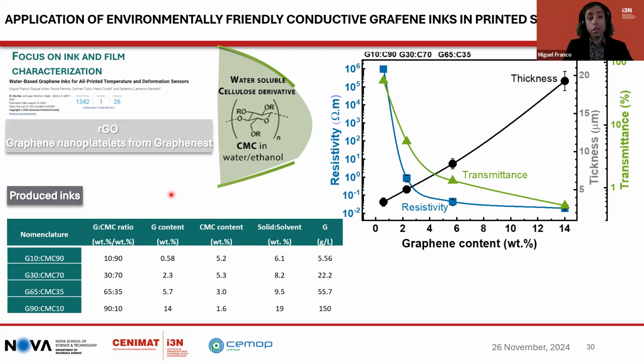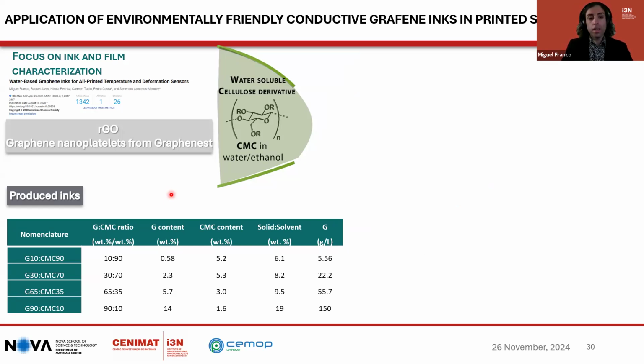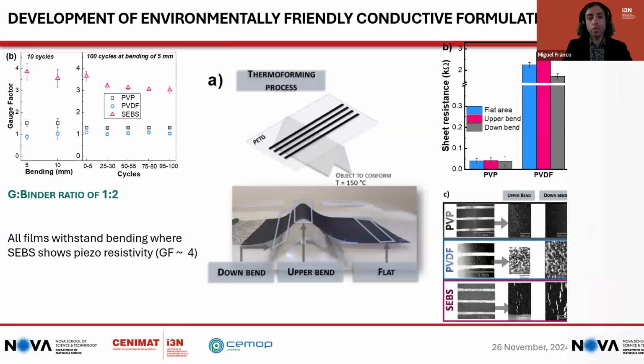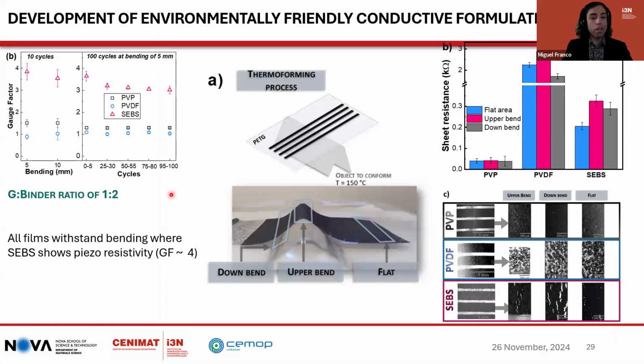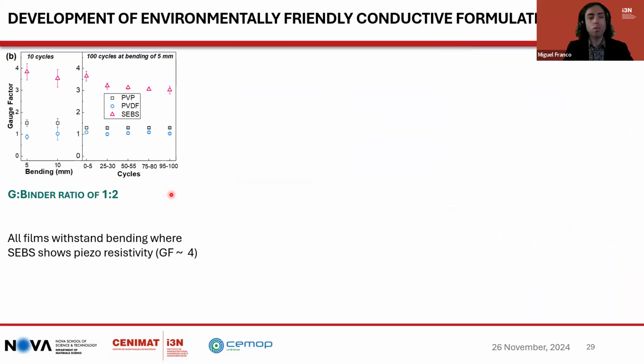For printed electronics, we tend to use reduced graphene oxides. But there is another interesting approach, for example for sensor fabrication, on which Cenimat has a lot of expertise: laser-induced graphene, where you use a laser beam to generate graphene. We did some challenges, but it's another interesting approach, also available in Cenimat.